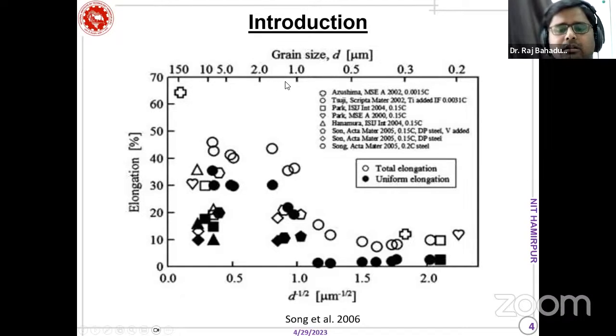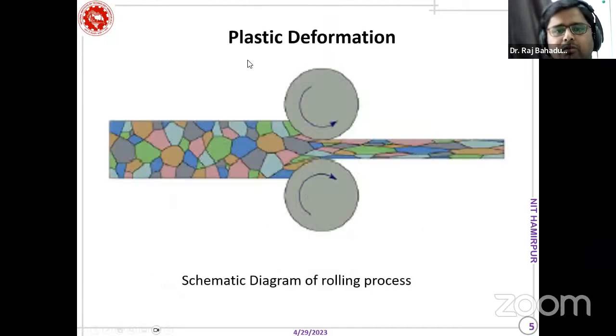And if you see carefully, in the region of 1 micron to 10 micron, the ductility is very high. So the idea is to combine the two: a microstructure of ultrafine grains together with some coarser grains in the range of 1 to 10 micron, then we will have optimum properties in the material, with high strength and high ductility. Coming to plastic deformation, this is a schematic of plastic deformation by rolling, in which we are deforming the material plastically.